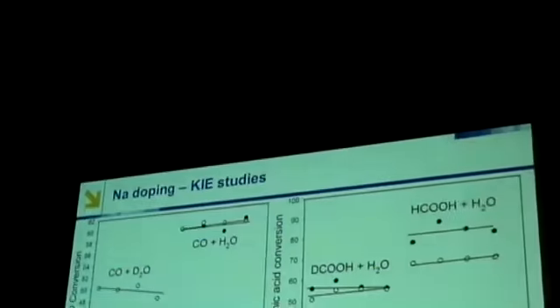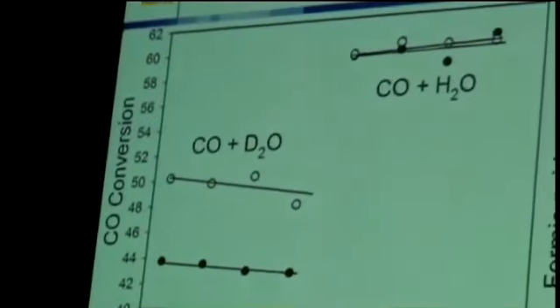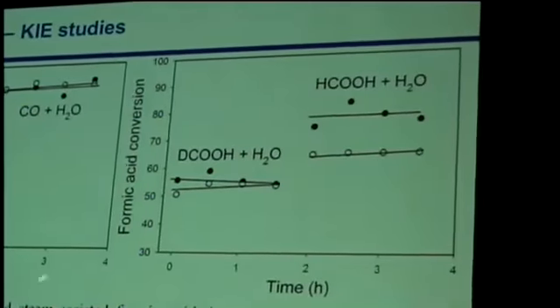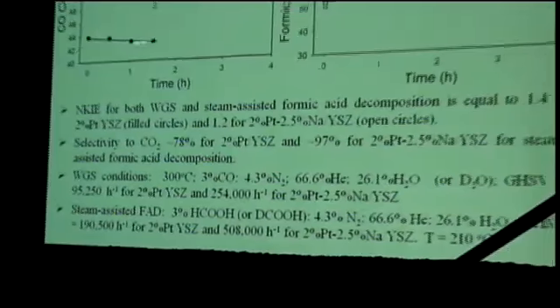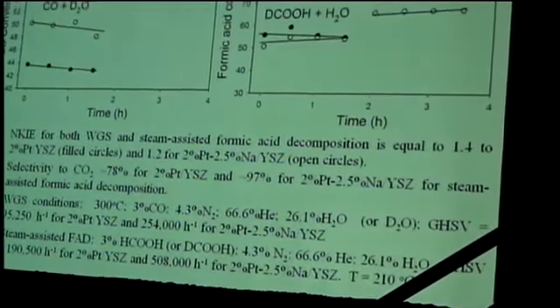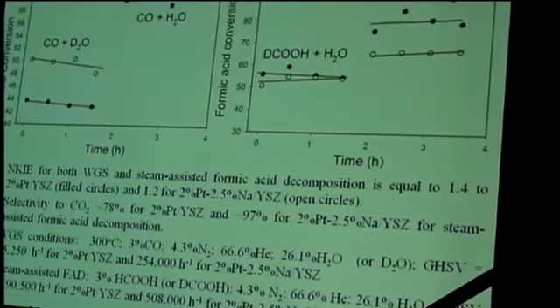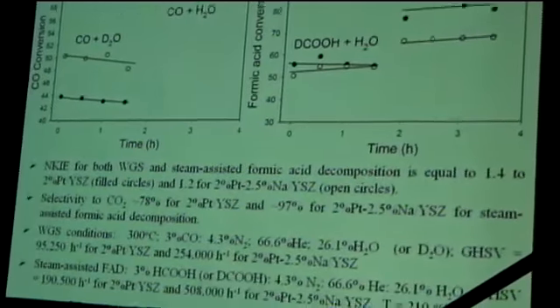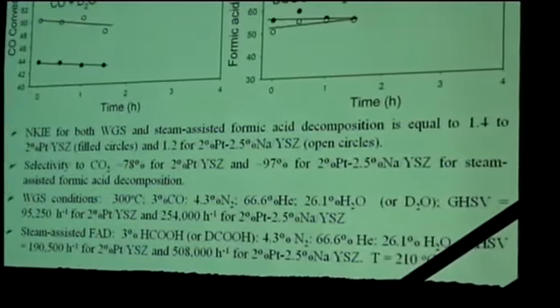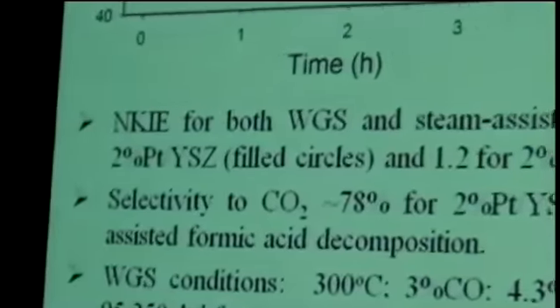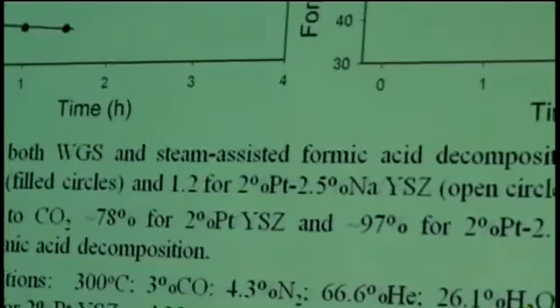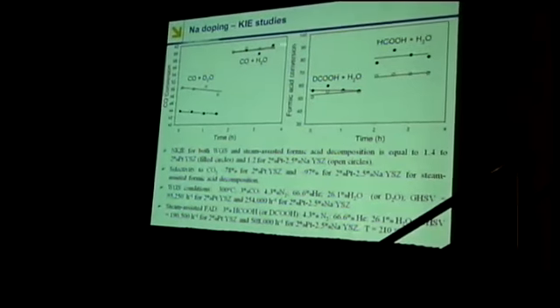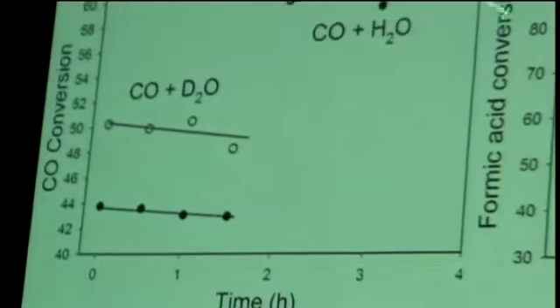So what we did was we carried out some kinetic isotope effect studies of our own, and we switched from deuterated water to H-labeled water for both the undoped catalyst, which is shown here, and the sodium-doped catalyst. And we should see a change in the rate if the CH bond breaking is the rate limiting step. And we certainly do see a change because the CD bond is a stronger bond than the CH. But if we're weakening the CH bond by alkali doping, then we should see a decrease in the kinetic isotope effect. And we do. We see a decrease from about 1.4 for the undoped to about 1.2 for the sodium doped.